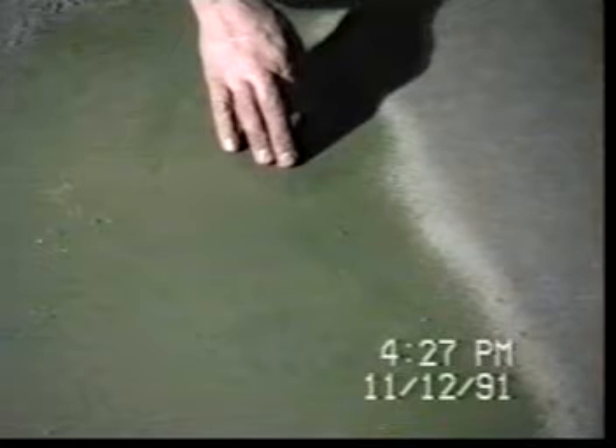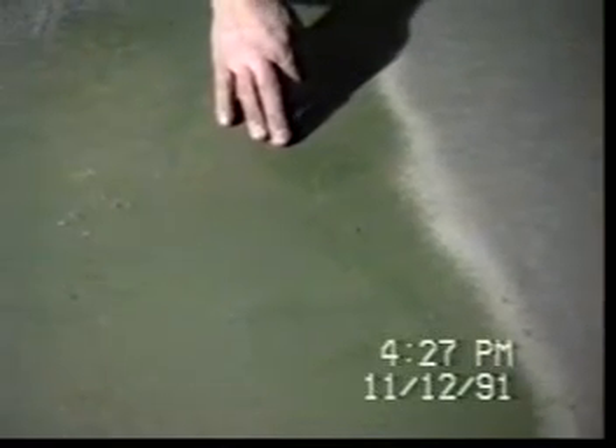This is the existing coating that's in the tank. What we have here is 6 mils of metallizing aluminum. We have 6 mils of polyurethane coating that's on top of that, and the coating has failed in the metallizing, and it's blistered quite bad. Here's an area right here.